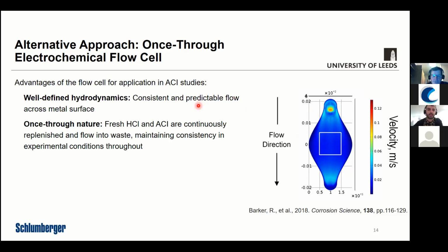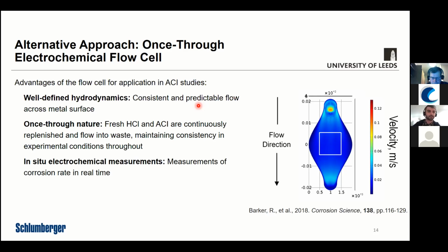It's a once-through cell, so we would position the cell in between a beaker, from which we would continuously flow hydrochloric acid or whatever electrolyte we'd want into the cell, which means that we're constantly replenishing hydrochloric acid and acid corrosion inhibitors. So the concentration flowing into that cell is never influenced by the corrosion processes. We can do the electrochemical measurements. It's obviously very useful to determine mechanisms and corrosion rates in situ.